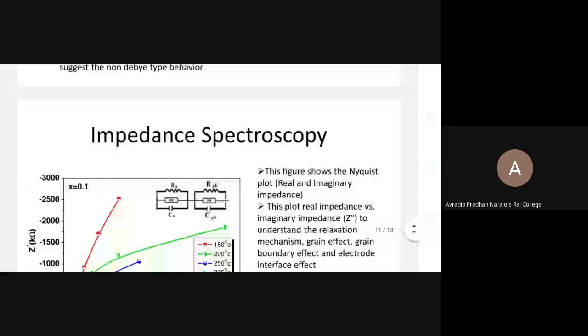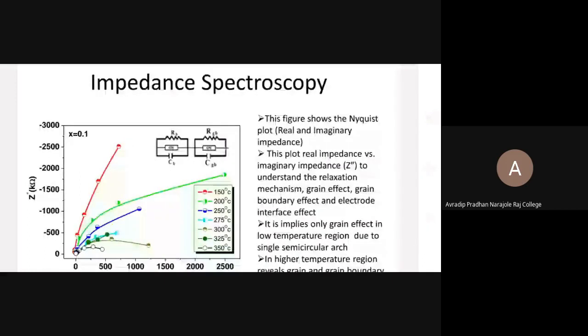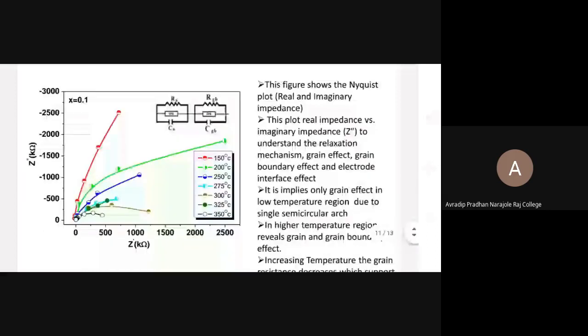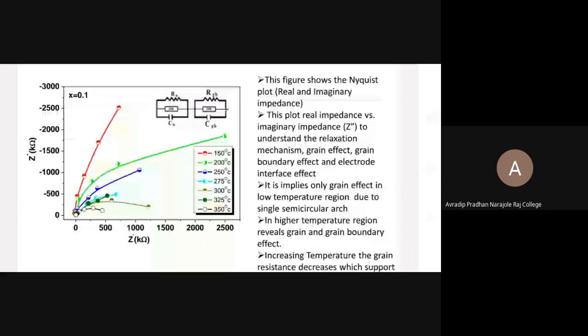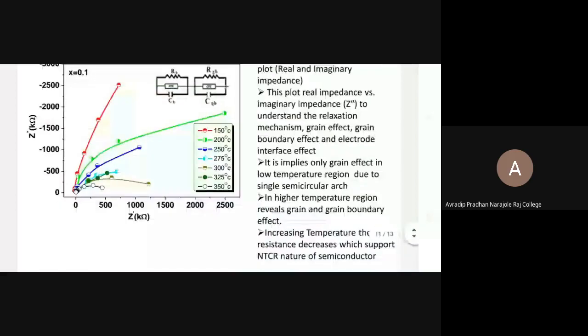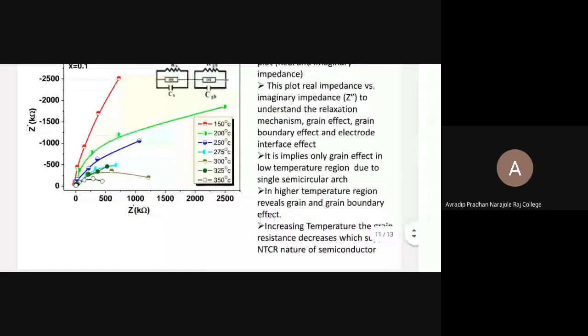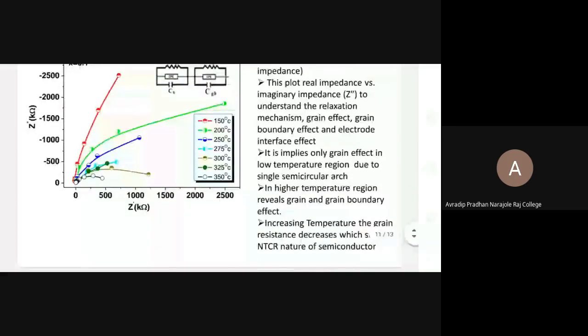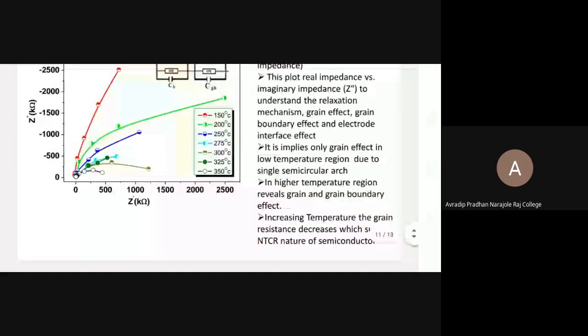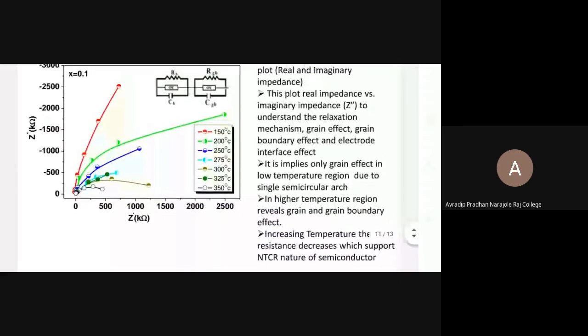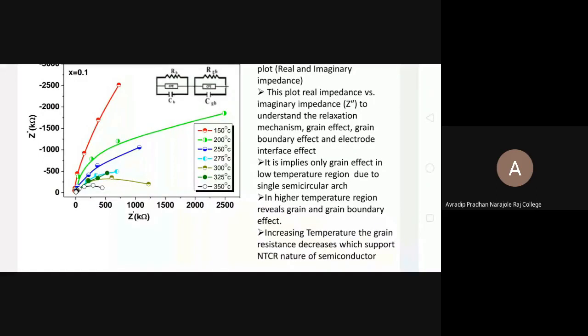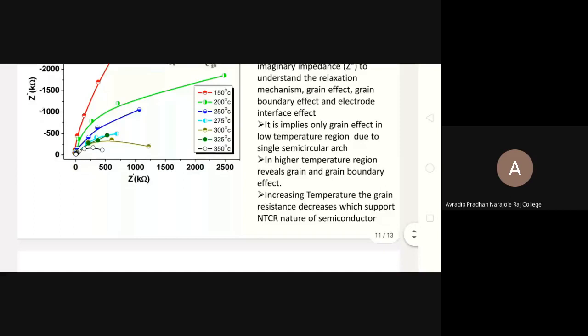The next slide is the impedance spectroscopy. This figure shows different temperatures from 150 degrees centigrade to 350 degrees centigrade. This Nyquist plot shows the real impedance against the imaginary impedance. Only one semicircular arc is represented in the lower temperature region, which suggests the grain resistance. When the temperature increases, the semicircular arc is depressed towards the Z prime axis, that is the real impedance axis, which also reduces the grain resistance. When more than one semicircular arc appears, it implies that grain boundary resistance is also present in this material. So with increasing temperature, the resistance decreases. This shows the negative temperature coefficient of resistance, that is NTCR behavior of a semiconductor.